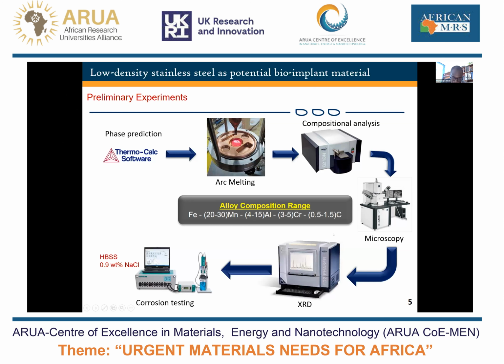We did microscopy and XRD analysis to establish the phases, because depending on the alloying elements and the amount of the alloying elements, you could have different grades of low density steels or low density stainless steel. And after we did this, we got some results, and those results made us consider carrying out thermomechanical processing, which I will also talk about.